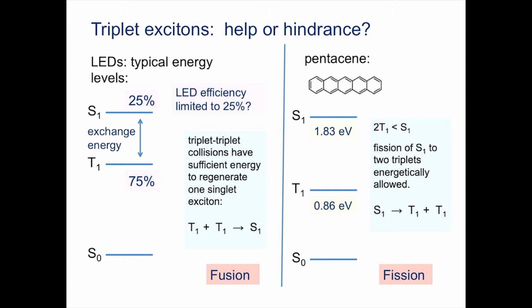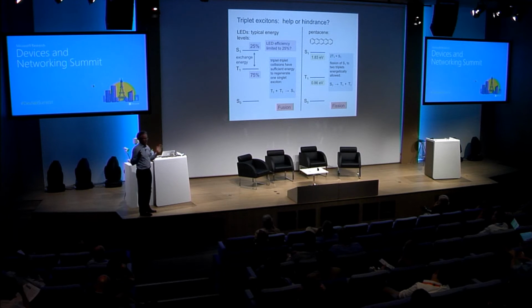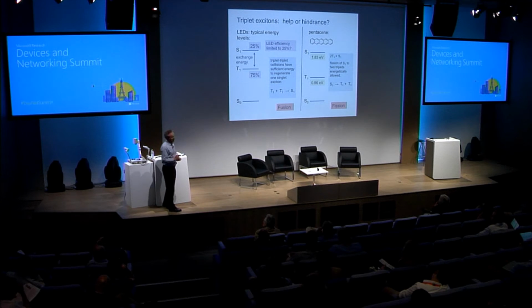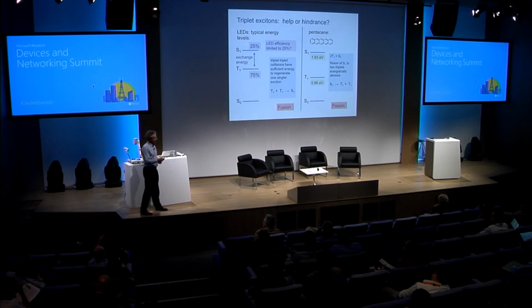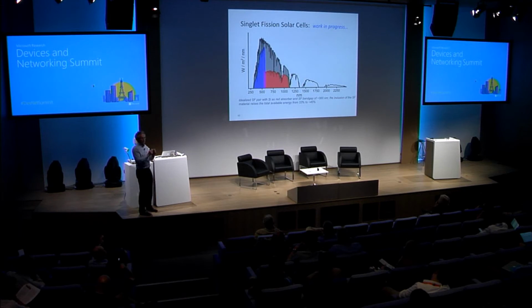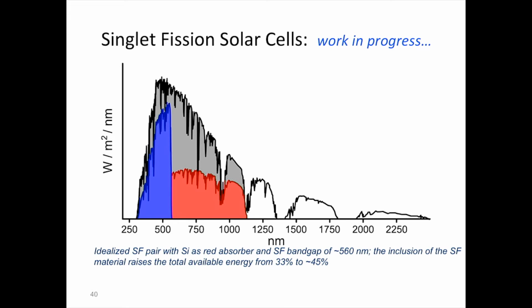But then there's a reverse process where if we can really make the triplet very low energy, when the triplet becomes half the energy of the singlet, they can split. The singlet can split to form a pair of triplets. It's a very interesting maximally quantum entangled pair of triplets that's overall spin 0. And the amazing thing is that that happens incredibly efficiently in some materials. It happens in 10 to the minus 12 of a second, so anything that happens that fast is going to be very efficient. So the scheme is we can use some of those materials that do that, and if, and there are plenty of ifs, everything would work, then we can regain more efficiency in the visible part of the spectrum by getting twice the photocurrent from the visible.